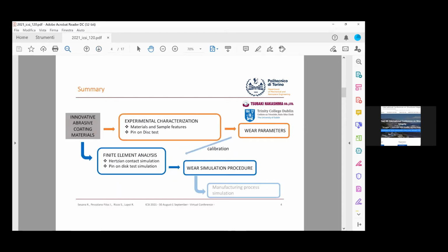As a first step, we perform an experimental characterization before performing the wear test. Then the experimental setup for the wear measurement parameters. After the experimental approach, we perform a finite element analysis and the wear simulation procedure. The last step is used to simulate the manufacturing process.